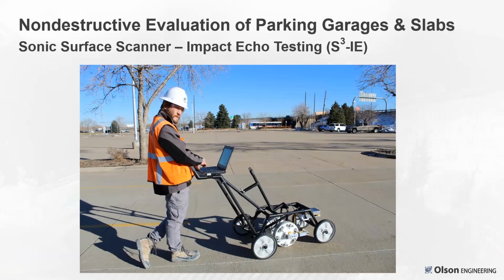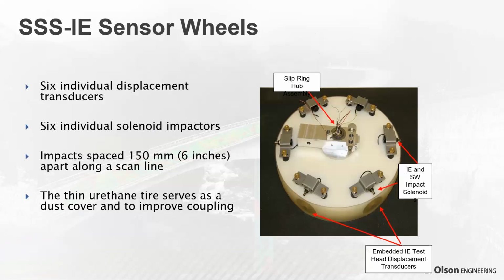But the sonic surface scanner can be used in large areas and can collect a lot of data very quickly. As seen here, this is our SSS, our sonic surface scanner, in use. It is a larger version of the hand scanner that Larry showed in an earlier slide. It has multiple transducers. It can test, as I noted, large areas of concrete. You can test at a walking speed, and it works on rougher surfaces than the hand scanner. So this will work on broom finished surfaces, tined surfaces, surfaces with some freeze thaw damage or other degradation, as we'll see in one of the examples I'll be showing.